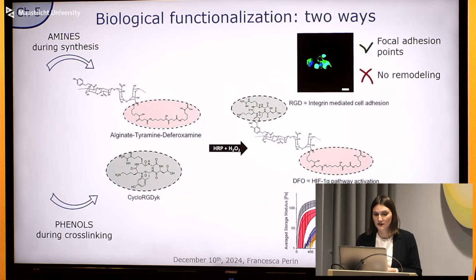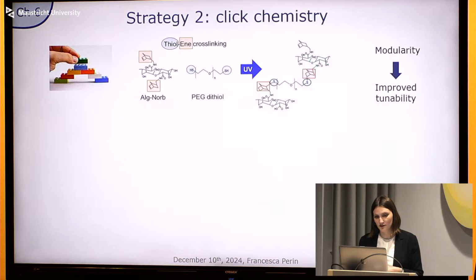So when figuring out how to move forward with the issues that we found, we thought to move to a different system, which is presented in chapter 6, and which here I schematized with Lego blocks, because we moved forward to click chemistry, in particular to thiol-ene chemistry. In thiol-ene chemistry, we synthesize alginate norbornene, and then to create a network, we use dithiol crosslinkers. Here you can see PEG dithiol, but we also use different ones that are described in the chapter.